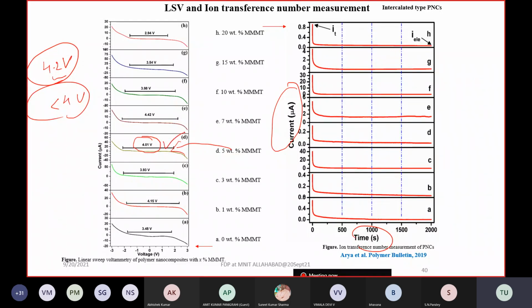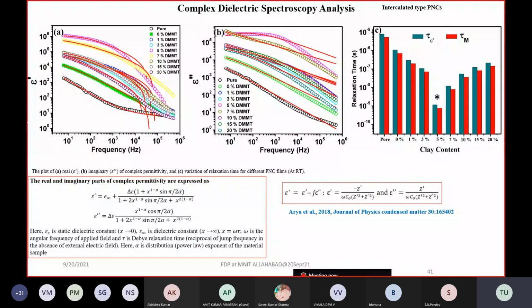This is actually the dielectric response of the same solid polymer electrolyte in order to find out the relaxation time. Actually, this epsilon prime versus frequency and epsilon double prime versus frequency graph is going to be drawn and fitted, and epsilon prime is going to be calculated using this formula: minus Z double prime over omega C naught times Z prime square plus Z double prime square, where Z prime and Z double prime, you all know, are the impedance in the real and imaginary axes. Omega is the angular frequency, C naught is the capacitance in free space. So in this formula, epsilon prime and epsilon double prime have been calculated, and they have been fitted using the theoretically derived relations. These two equations have been fitted here, and thereafter the relaxation time has been calculated, and you see the same where intercalations have been done.